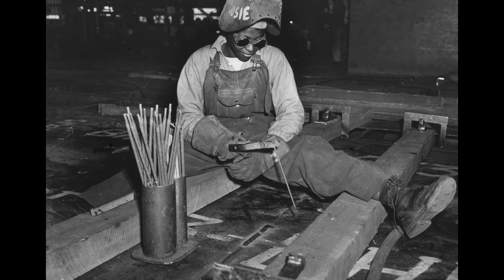When brittle steel met concentrated residual stress at a sharp corner, like a square cargo hatch edge, physics acted with merciless precision. A microscopic crack would form. In ductile steel, it would stop, absorbed by the material's ability to yield. But in brittle steel under tension, the crack became a sprinting fracture. The energy stored in those locked-in stresses fueled it forward. Sharp corners acted as multipliers, amplifying local stress by threefold or more. The crack would accelerate, sometimes faster than the speed of sound, tearing through the hull before any frame or bulkhead could halt it.